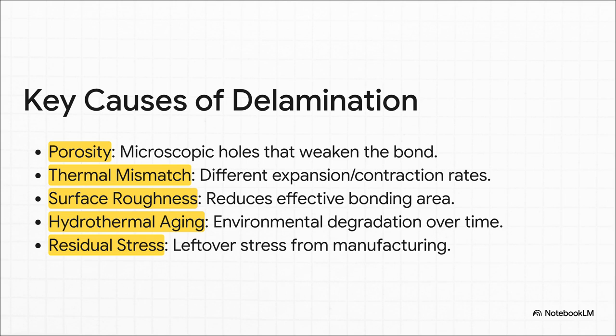Improper surface roughness is another one. It can sabotage the bond by not giving the coating enough to grab onto. Hydrothermal aging is that slow, sneaky damage that just comes from exposure to heat and moisture over time. And finally, there's residual stress, a hidden tension from the manufacturing process itself, constantly trying to pull the coating away from the inside.